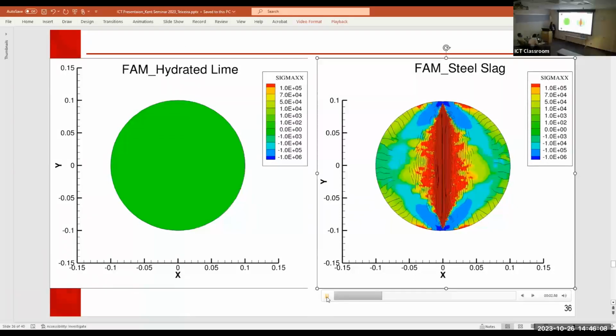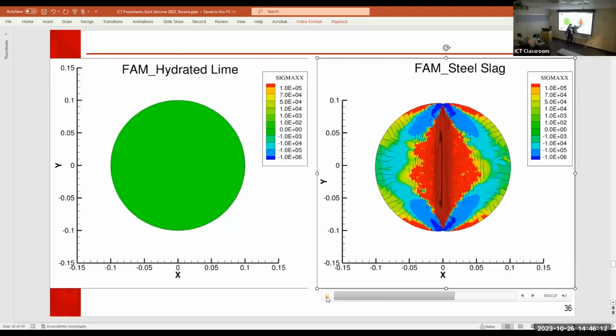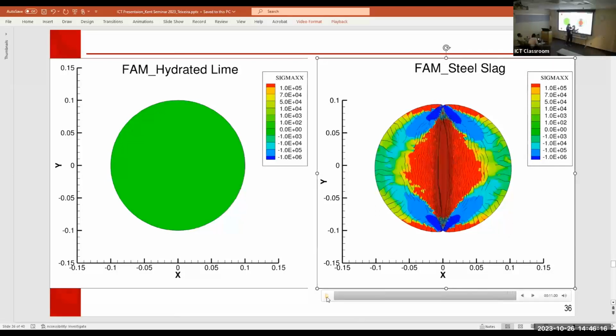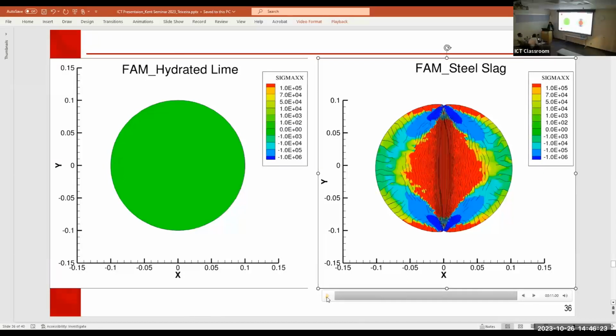You can see that you have a lot of cohesive zones being inserted, which gives compliance to the material, and damage dissipation through viscoelasticity, but the crack doesn't open. So that shows that this mixture is more resistant to cracking.